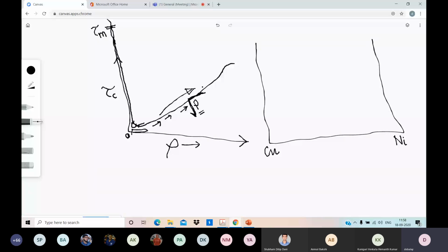Dislocations cut each other and form some kind of configuration that is immobile. Sometimes two dislocations react and form an immobile barrier, like when two cars collide and the road gets completely blocked.